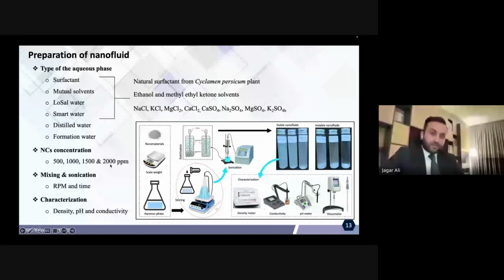So for this project that I'm presenting here, we use different types of aqueous phase of the fluid. For example, surfactant, mutual solvent, low-salinity water, smart water, distilled water, and formation water, in order to check the effectiveness, the performance of the nanocomposite with different types of the solution in order to obtain the best one. Even the surfactant that we used here is a natural surfactant from the Cyclamen persicum plant. The mutual solvent is ethanol and methyl ethyl ketone, and we built the smart water solution using these different salts.